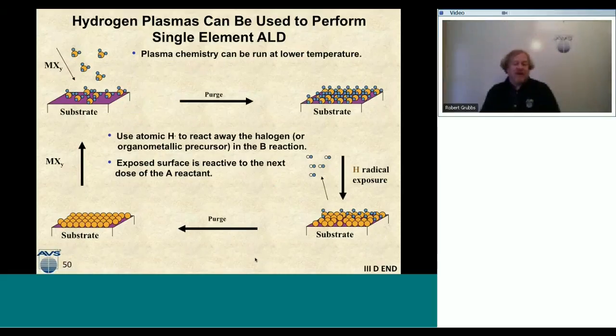All right, so the last way we can do this is hydrogen plasmas. Here we come down with an organometallic precursor, probably in a physisorbed state, and then we expose it to hydrogen radicals, and the radicals will strip away all of that organometallic precursor, turning it into methane or water or whatever the organic is. Then I'm left with this very naked and very vulnerable metal surface, and this surface will enable more of the organometallic to physisorb down onto it. Again, I expose it to hydrogen, and I strip away all the organometallic material, which reduces the metal down to the base metal.